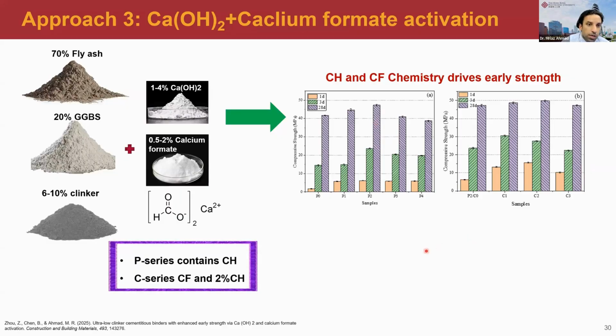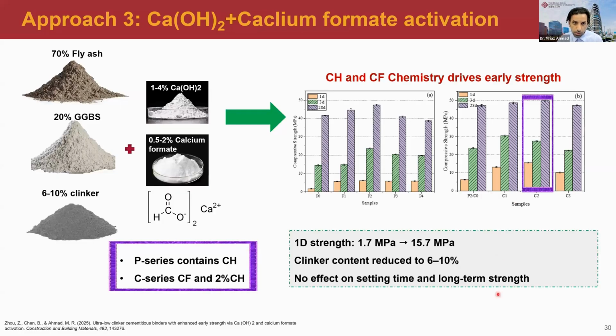And further, because the compressive strength is still very low and does not meet the industry standard, it is around 6 megapascal only. So in the further optimization, we added some calcium formate. And we could see that at 1 day, we could achieve a compressive strength of 15.7 megapascal, which is a significant boost in the compressive strength, given that clinker content is only in the range of 6%.